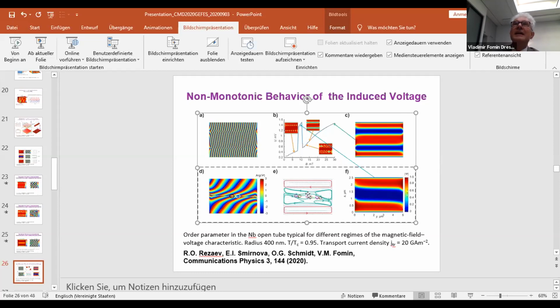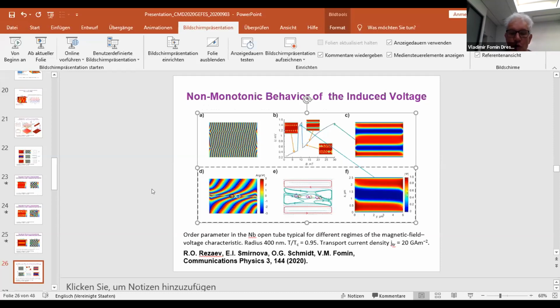What is still interesting here in the central part, that in place of two loops of screening currents, when this transition period occurs, we see another two loops, and just in between of these additional loops of screening currents, we have a locus of the formation of vortices and anti-vortices. So they are in the middle. A topological transition here is confirmed by the fact that we have now more disconnected loops of screening currents in the system. I must rush now.